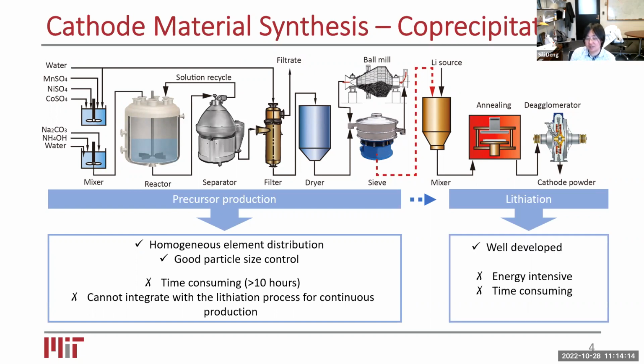And the lithiation process is definitely needed to introduce lithium. And because of this solid phase mixing, the uniformity can be achieved only after a relatively long time of annealing. To give you an idea, it's about 700 to 800 Celsius, and it can be as long as overnight, right? So for the entire process for a single batch, we are talking about the order of days. So this entire process is time consuming, energy intensive, and as you could imagine, all of this would add to the manufacturing cost of lithium batteries.